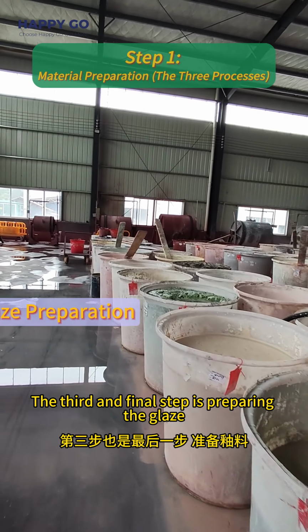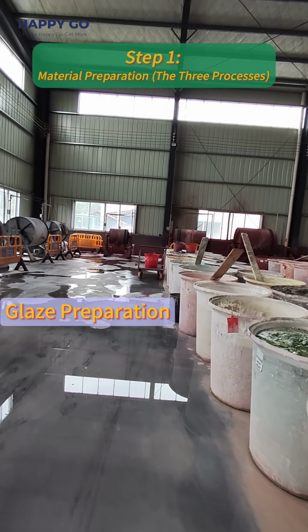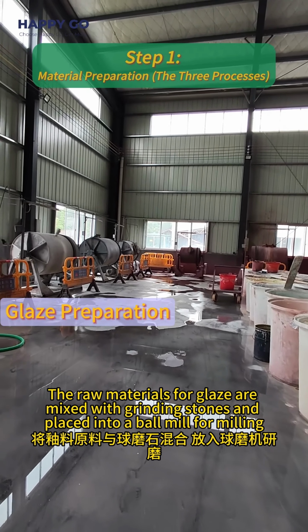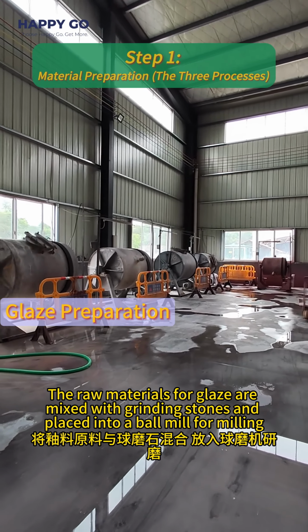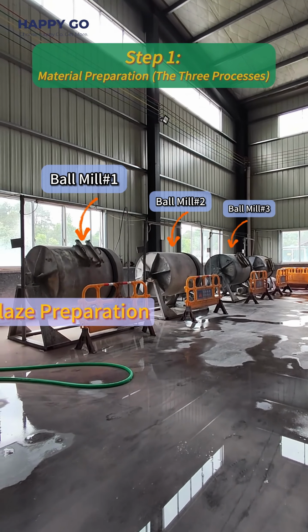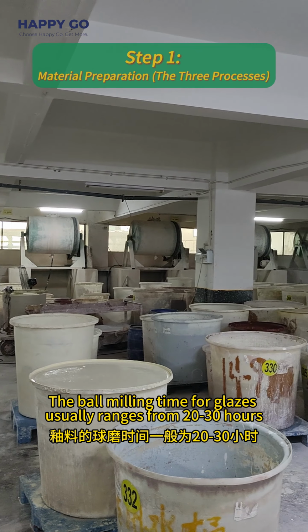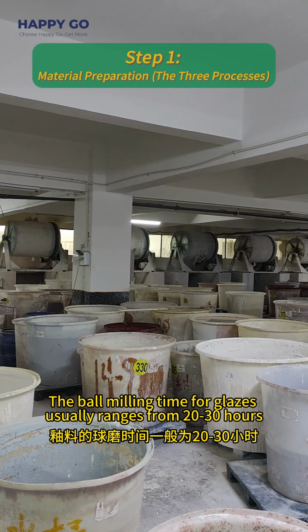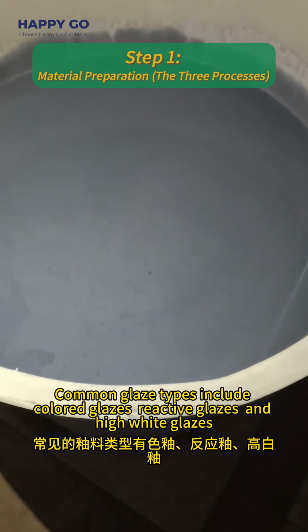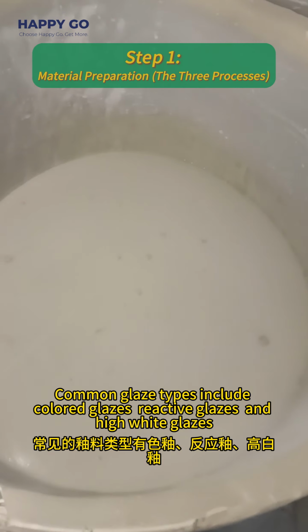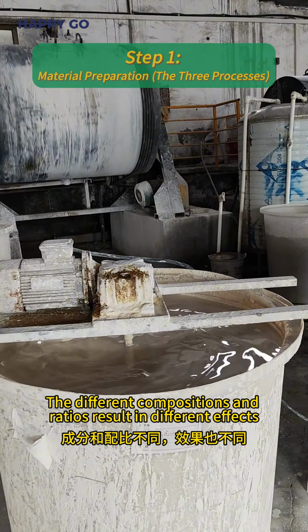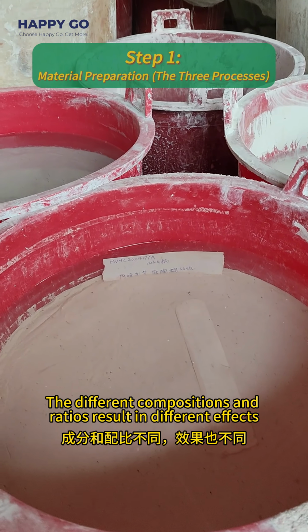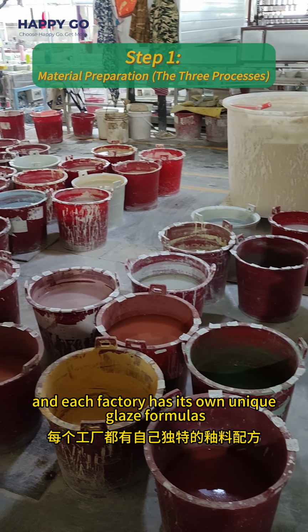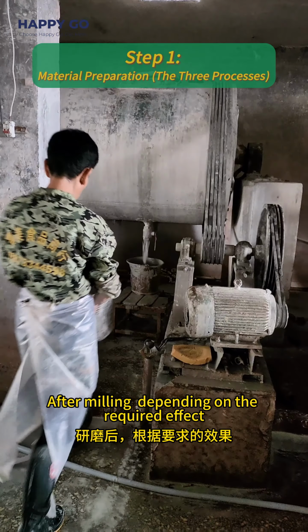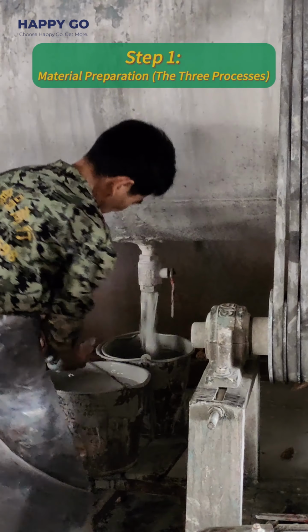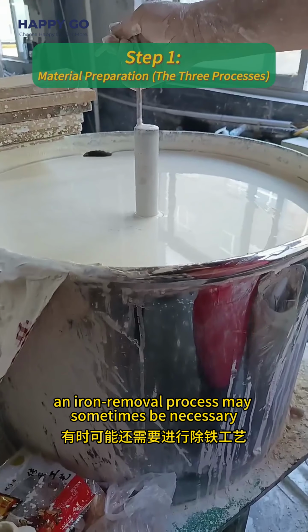The third and final step is preparing the glaze. The raw materials for glazing are mixed with grinding stones and placed into a ball mill for milling. The ball milling time for glazes usually ranges from 20 to 30 hours. Common glaze types include colored glazes, reactive glazes, and high white glazes. The different compositions and ratios result in different effects, and each factory has its own unique glaze formulas. After milling, depending on the required effects, an iron removal process may sometimes be necessary.